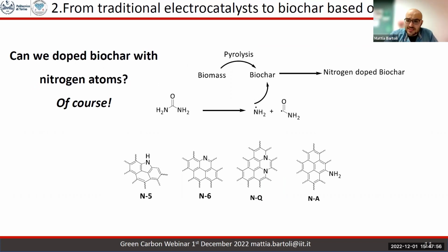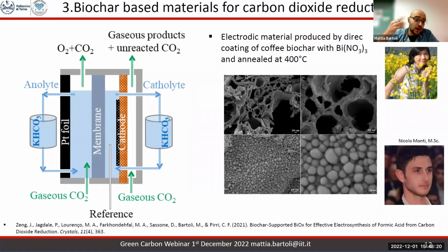Also, we simply tried to use urea instead of thiourea, just to dope the system by thermal annealing, of course, in this case, with nitrogen. So we create a portfolio of materials tailored with heteroatoms or nanostructures that could be used for different kinds of electrocatalytic processes.